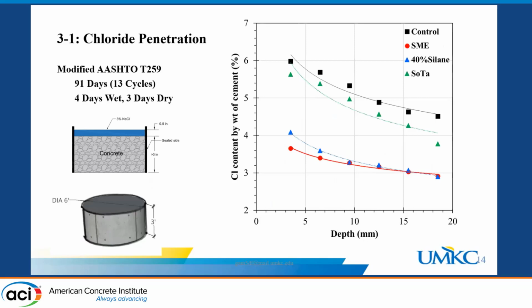The third objective of our research is chloride penetration, or chloride performance. We followed the methodology described by AASHTO T259. The only difference is that instead of ponding our chloride solution for 91 days, we followed 13 cycles, equivalent to 91 days, of 4 days wetting and 3 days drying, because we want to see the effect of wetting and drying on chloride penetration. We can see here again that all of the sealer treatments reduce chloride penetration, but soy methyl ester and silane reduce it most effectively compared to sodium tartrate.